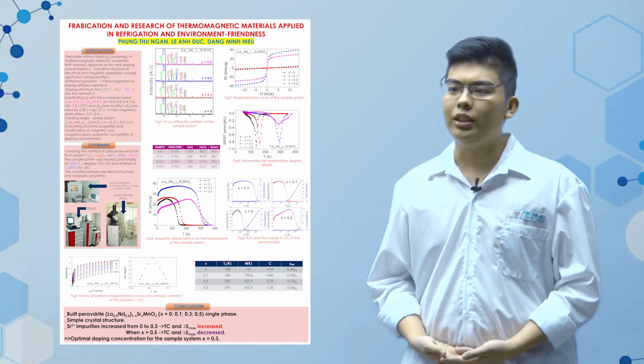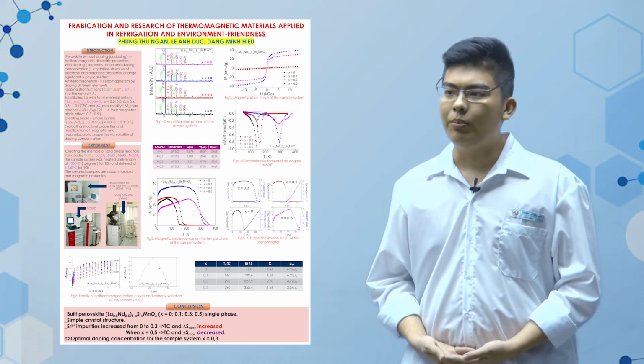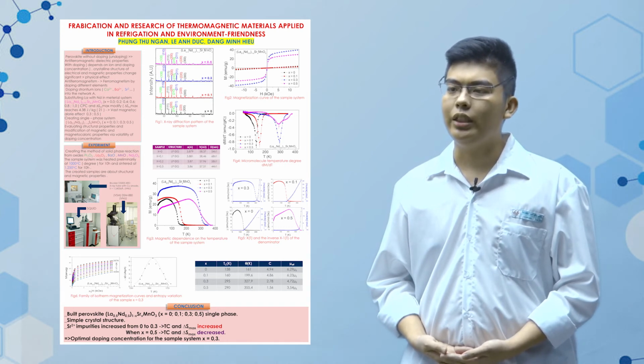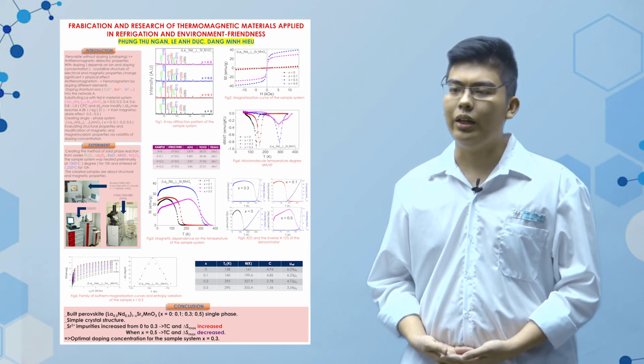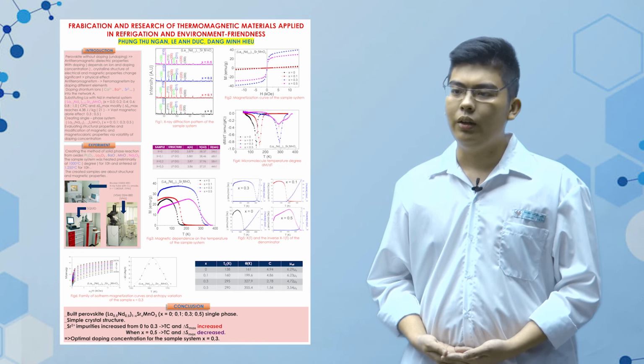Moving on, Figure 3 is magnetization dependence on temperature of the sample system, and the differential form of magnetization, dM/dT, is in Figure 4. From the M-T curve, we can calculate the kappa minus 1 and kappa. The Curie temperature was determined and listed in Table 2. When x increases from 0 to 0.3, the Curie temperature significantly rises, but when x reaches 0.5, the Curie temperature has a downtrend. It's clear that x equals 0.3 is the best sample. We got the highest Curie temperature, 295 Kelvin.